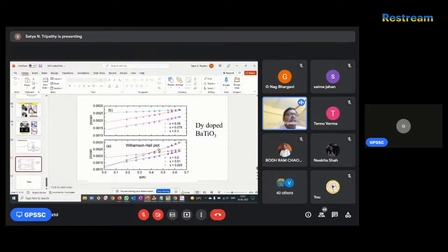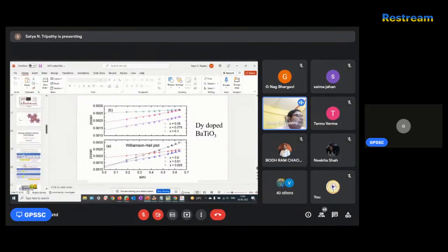This one we call Williamson-Hall, and here particle size basically ranges from, this is a barium titanate solid state synthesized sample, and I remember this is basically around more than 100 nanometer. Okay, so all the time a nano sample we basically understand as 100 nanometer and below.